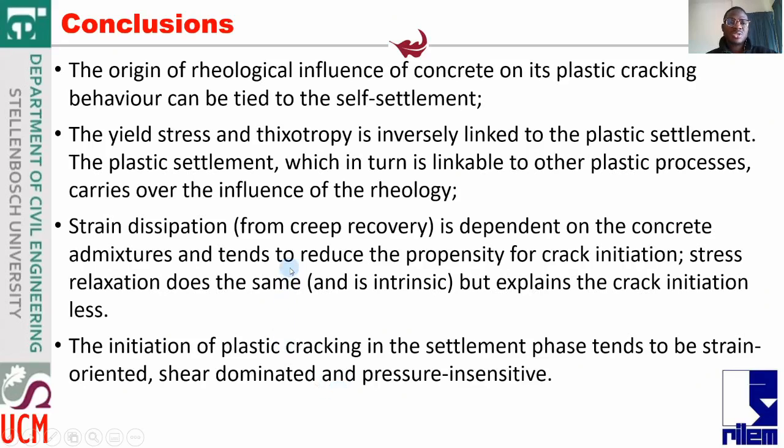Now to the conclusions. Some of the basic conclusions are these: that the origin of rheological influence of concrete on its plastic cracking behavior can be tied to the self-settlement. The settlement is the major origin of rheological influence of concrete. The yield stress and thixotropy are inversely linked to the plastic settlement. Then the plastic settlement, which is in turn linkable to other plastic processes, carries over the influence of the rheology.